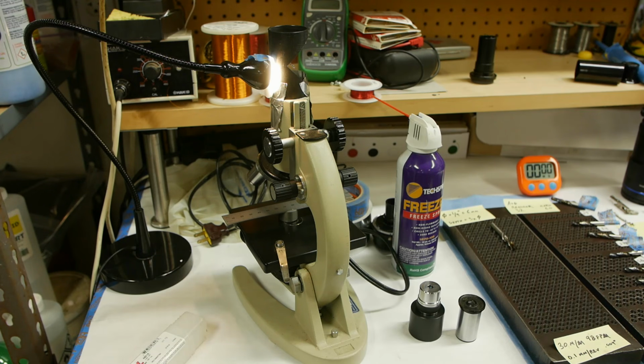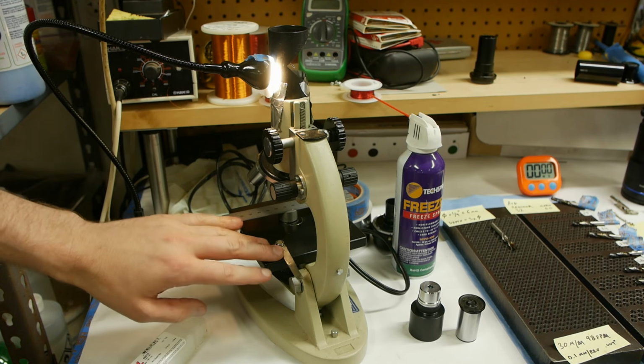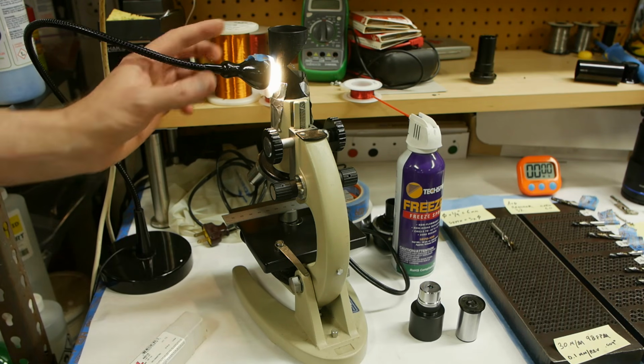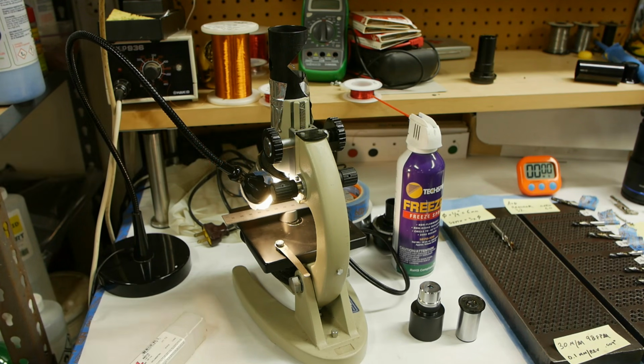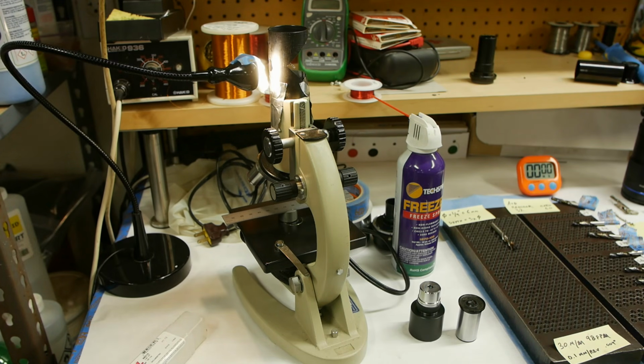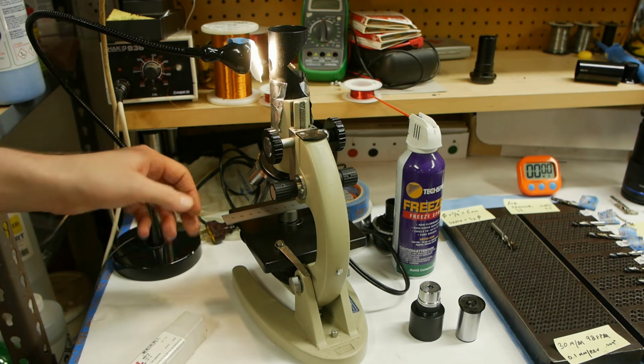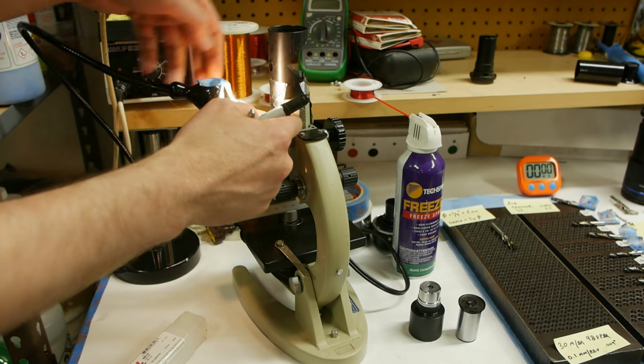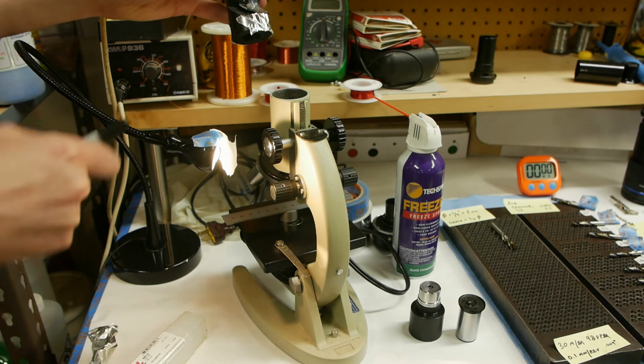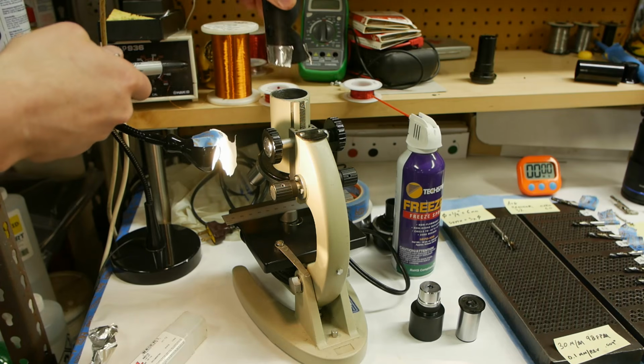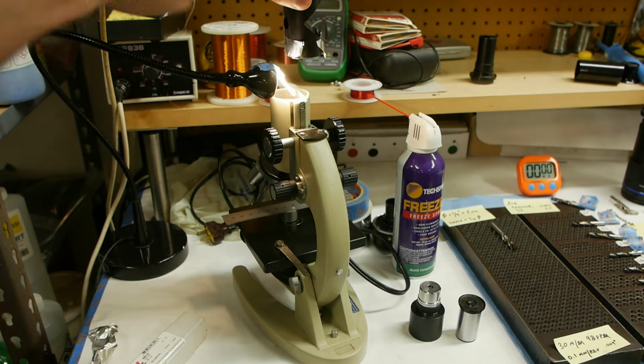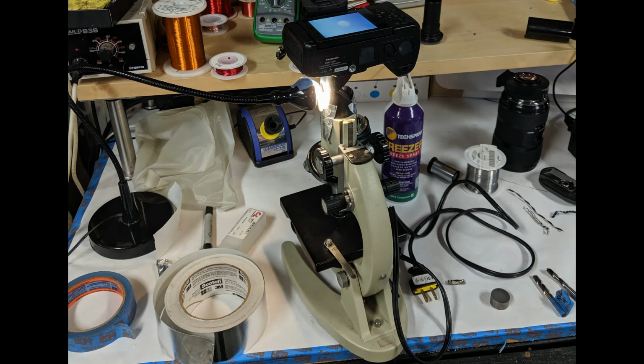And then we have to put it into a microscope where the light comes from the top. Most biological microscopes like this one work by shooting the light up from the bottom, or occasionally you can aim it in from the side like this. But it doesn't work for getting these really nice crystallographic images because the light has to be coming exactly on axis with the viewing angle, or otherwise this effect doesn't work where you're looking at the very tiny differences in surface quality. So I hacked together this really cheesy setup. It's basically just a piece of plastic that I actually used in another experiment, my Raman spectrometer, with a beam splitter here. I put this on and shined some light in here and then put the camera on top and was actually able to get a not bad result.